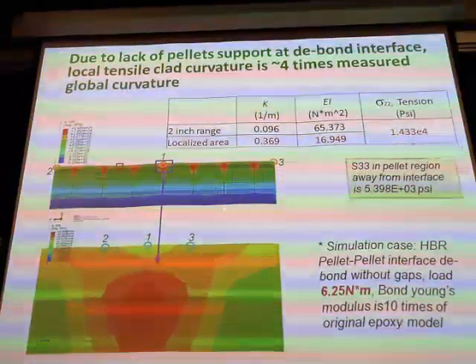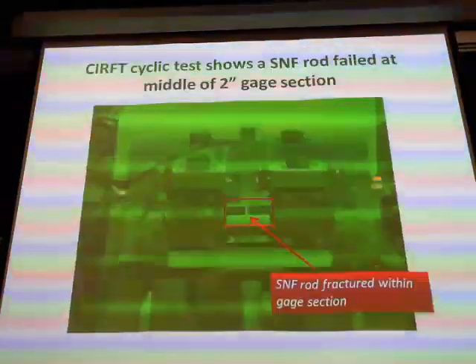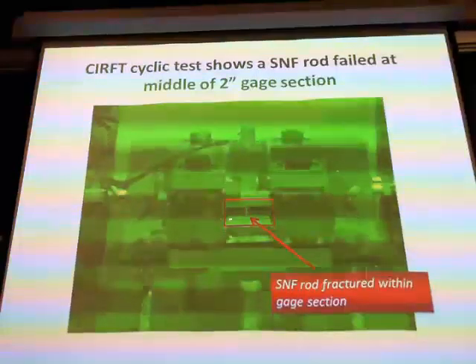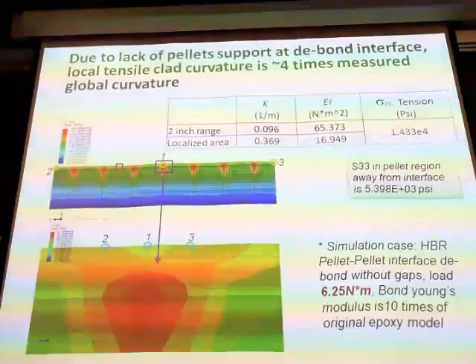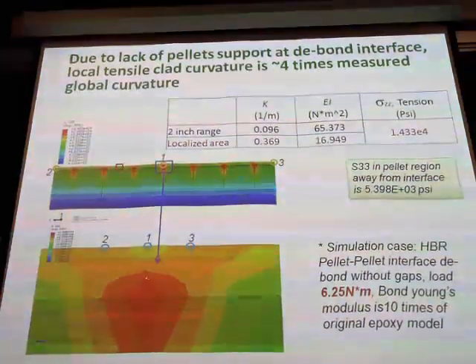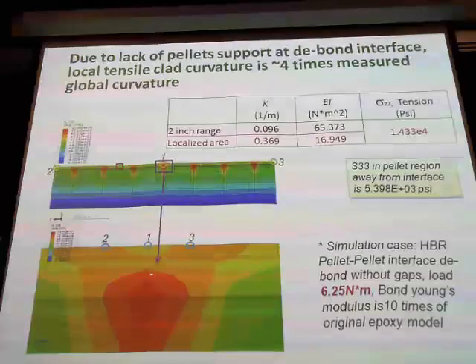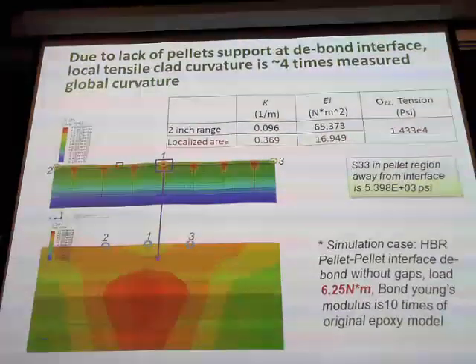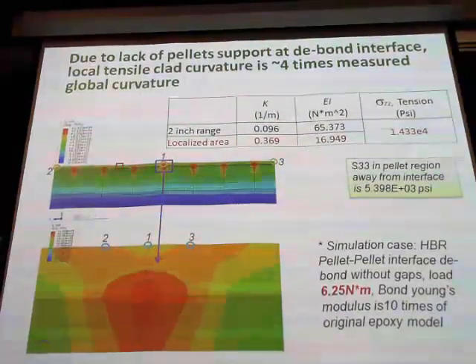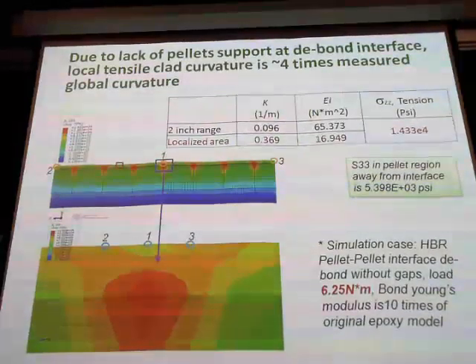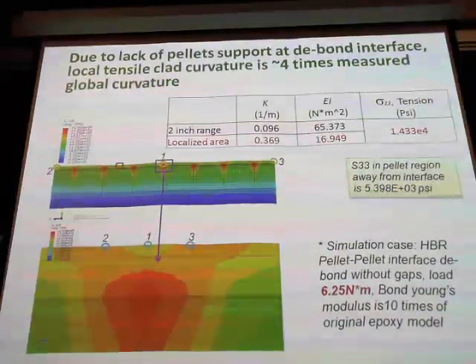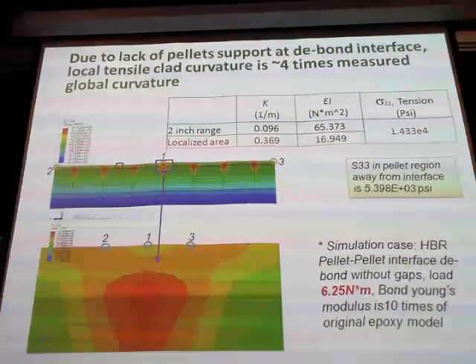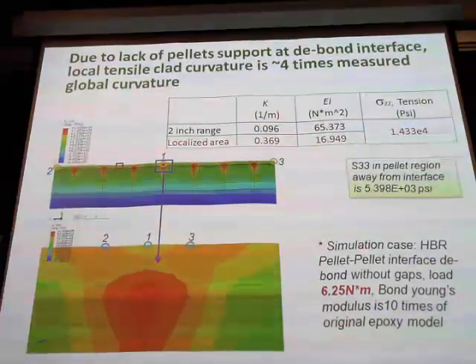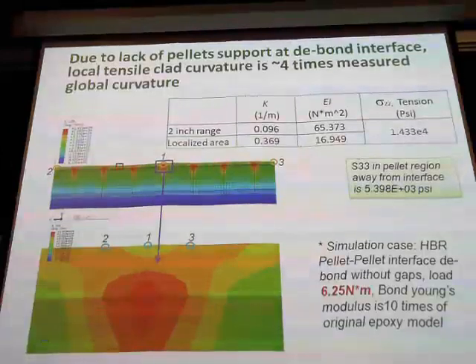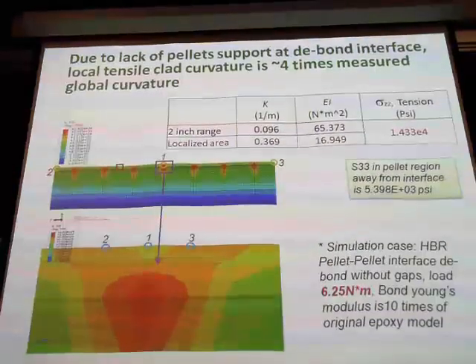And the really important thing I want to emphasize is the global response are curvature measurements, but a local stress concentration, no way you can measure them. For example, the maximum stress is not on the surface, it is underneath. And the local curvature is about four times the global curvature. So those need to be borne in mind. You deal with composite material, not a single isotropic material. So the stress concentration is very important, cannot be neglected.